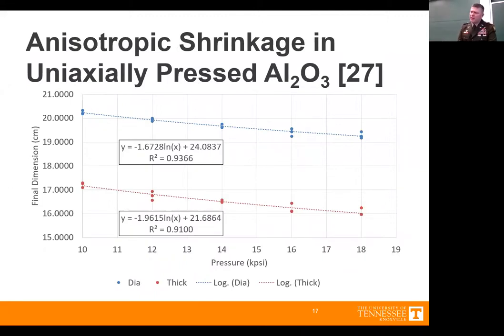So this is just some data that I was able to obtain from some industrial work. You know, Oak Ridge is a great location, University of Tennessee. They're ideally situated to interface with some of the industries that are important to a lot of the work that we do. So I was able to actually get some of this data from Dave Johans. And so just looking at this, what he's showing here is that they took an aluminum oxide object and they uniaxially pressed it so that it had the same dimensions in the radial and axial direction. So it was a perfect right cylinder with, for example, if the radius was 1 centimeter, the height was 1 centimeter, right? And then they sintered that object, and they did this for multiple different trials with multiple different applied pressures for their uniaxial pressing.